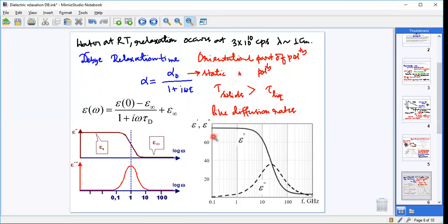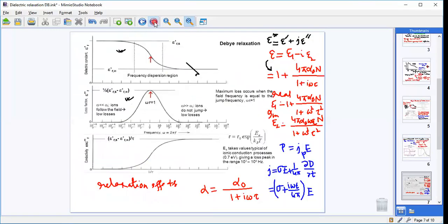So the relaxation times in solids are usually much longer than in liquids. This behavior is somewhat parallel to the behavior of diffusion rates in liquids or solids. Someone has related the observed dielectric losses in alkali halide crystals to the presence of lattice defects in the crystals, with considerable success. So moving on to the complex dielectric constants and the loss angle,